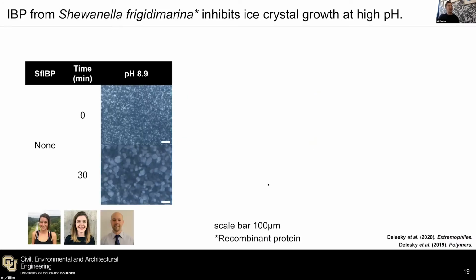So what we did is we looked at that solution. We took simulated pore solution of concrete, and we tested whether or not an ice-binding protein has this IRI, this ice recrystallization inhibition activity. So this is the data that you would get. This is for a pH 8.9 solution without any protein.